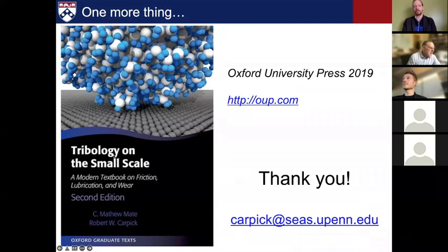So we took advantage of the fact that graphene has so few defects and we sort of avoided them and didn't look carefully for them. There is some other work where people have looked at friction contrast. Well, let me go back a step. Phil, actually, Egberts did look at what happens when you have steps. So that's one type of defect. And there is friction enhancement at steps because those are higher energy sites and you can get deformation and even folding up at those steps.